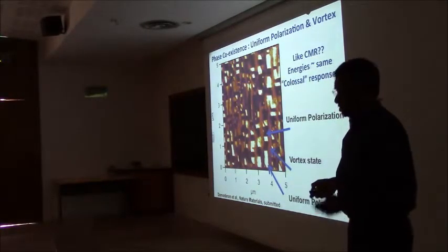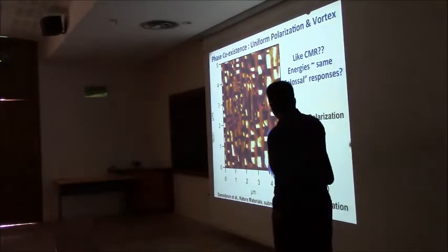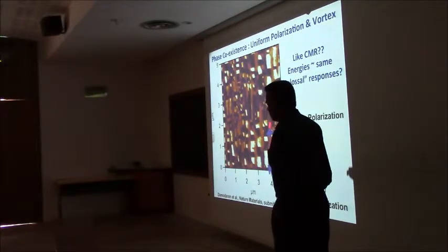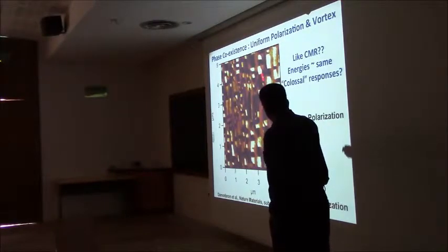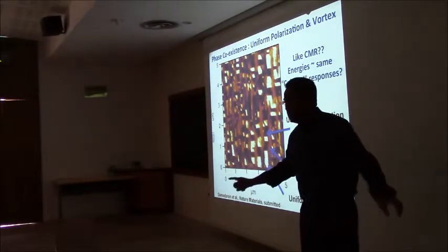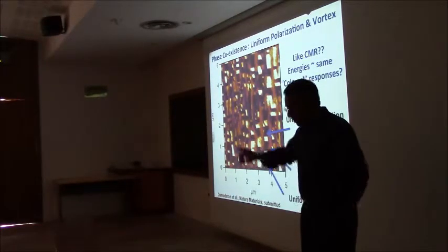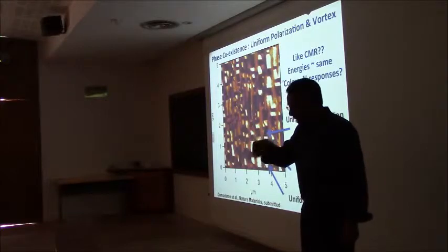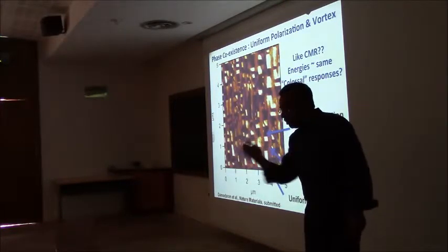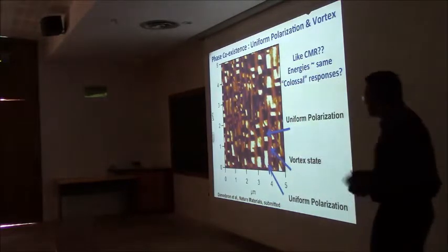What we saw was just staggering again, because we see this very nice fiber-like organized structure. These regions have very strong in-plane piezoelectric response. These are in-plane images. Again, I think you will talk about PFM tomorrow, on Monday, where you can measure what happens to the cantilever this way, or what happens to the torquing of the cantilever in plane. So all those components can show up.